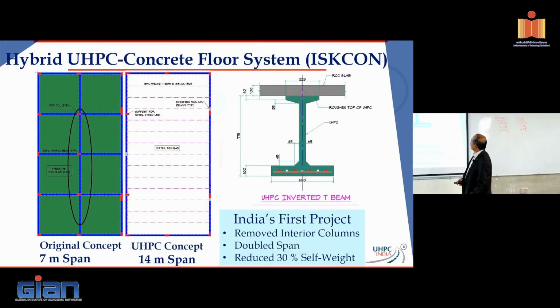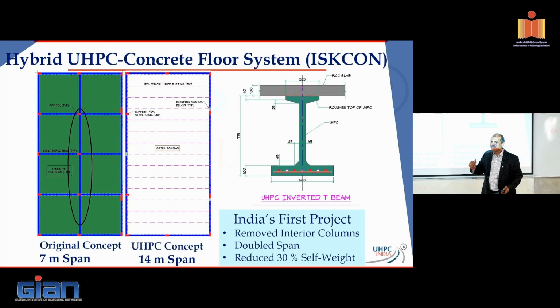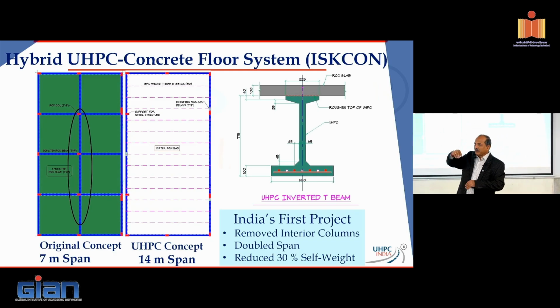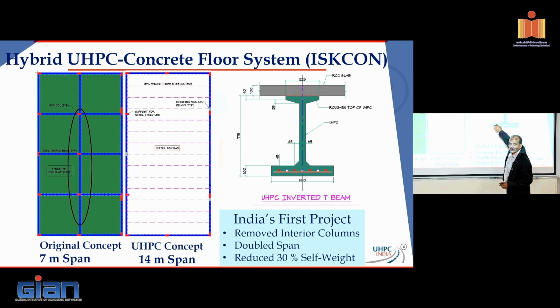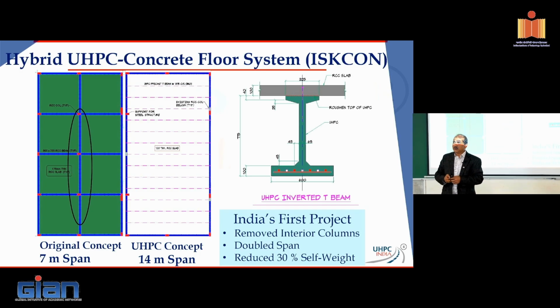So, this one was deeper, about 775. It was thin and deep. We didn't have any constraints with respect to that. We could come out thinner, shallower, and wider as well. So it really depends on what is acceptable on the site, what works out most efficient and economical, and what the parameters are. Could we have done that in 600 mm? Probably yes. We probably had to put more post-tensioning in it. Probably this would have been thicker. The web might have been slightly wider than what we had. So it's just a matter of what is more pertinent to that particular project at that particular time. Okay.